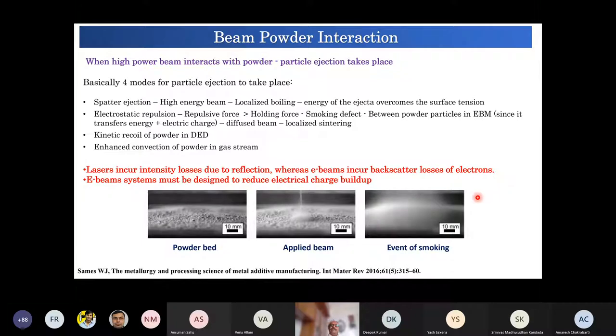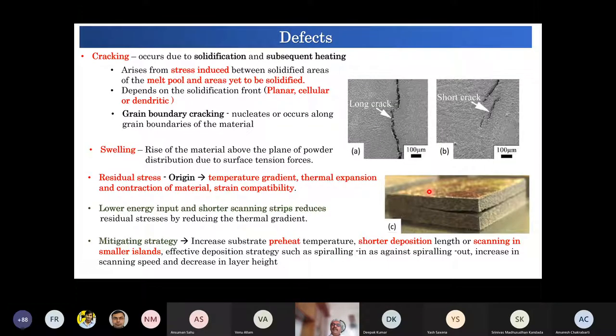So these parameters have to be optimized so that there is reduced electrical charge buildup, because here there is an interaction between the incoming electrons and the electrons of the metal, and this leads to a certain phenomenon that has to be controlled. There are other types of defects: defects related to solidification and defects related to cracking, solidification and subsequent heating and cooling. It can be cooling as well.